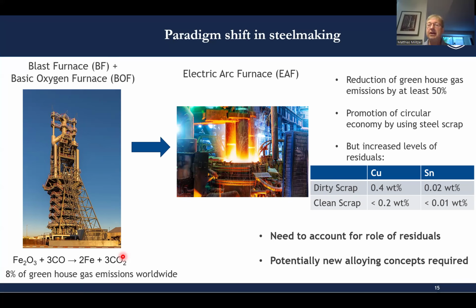But scrap contains impurities or residuals that are difficult to remove. Maybe the most important ones being discussed are copper and tin. If you look at the values in dirty scrap, we have upwards of 0.4 weight% copper and 0.02 weight% tin. And in clean scrap, maybe it's a factor of 2 or so lower, but nevertheless, it is still present.